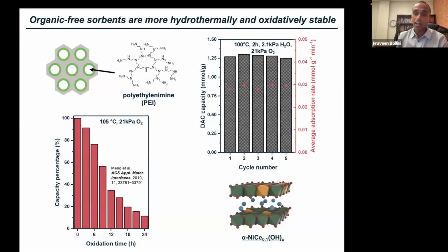In fact, one thing that I'll emphasize here is in many years or multiple years, we've not managed to deactivate our sorbents so far. So these are very, very robust to thermal cycling. They're hydrothermally stable and they're inherently oxidatively stable because they don't have any organics. The data specifically that you see on the right here is, I'm just showing you 5 cycles here. So you're adsorbing at 25 degrees Celsius in the presence of humid streams, and then you regenerate at 100 degrees C in steam in the presence of oxygen.